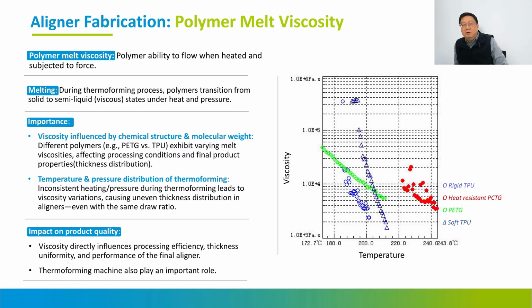What's the problem with the material absorbing moisture? It depends on the material, since different materials have different moisture absorption, and polyurethane is very sensitive to moisture absorption, because it reacts with the water. When you do the thermoforming process, it will create carbon dioxide if you absorb too much moisture. So if you use a retainer, you can see most of the aligner producers ask you to use up those dental sheets within about 20 minutes, because after 20 minutes, the moisture will go inside the aligner sheet. Then when you do the thermoforming, it will create a bubble.